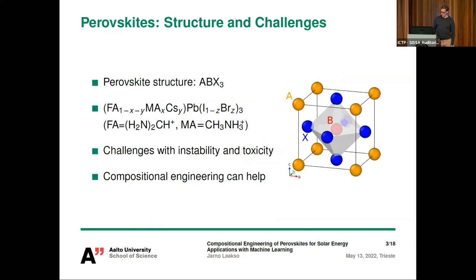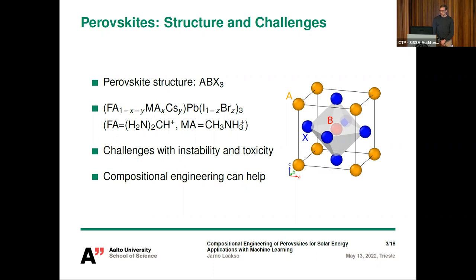So what are perovskites? Basically, any material that has this ABX3 atomic structure is a perovskite. But the most efficient perovskites seen on the previous slide are actually much more complicated — they have ionic mixing in multiple sites and organic molecules such as formamidinium and methylammonium. Even though their efficiencies are very high, they haven't been commercialized yet because of problems with instability and toxicity.